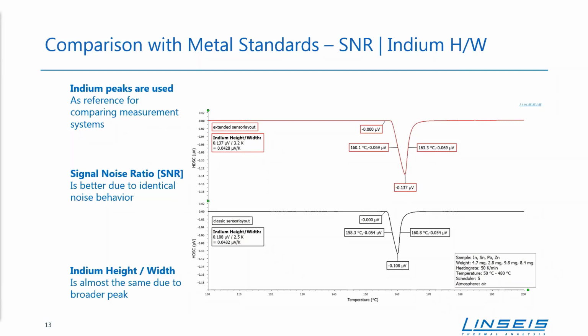But what's also important is the signal noise ratio, the SNR. I don't evaluate it here because it's quite simple to explain, because the reference site and the sample site above the sample sensor and the reference sensor is still the same. So of course, also the electronic is the same. So for this reason, also the noise is the same, but we can see our peak is around about 30% higher here in this case. And yeah, so the signal noise ratio is also better. So, okay, this is the result of signal noise ratio and indium height to width.